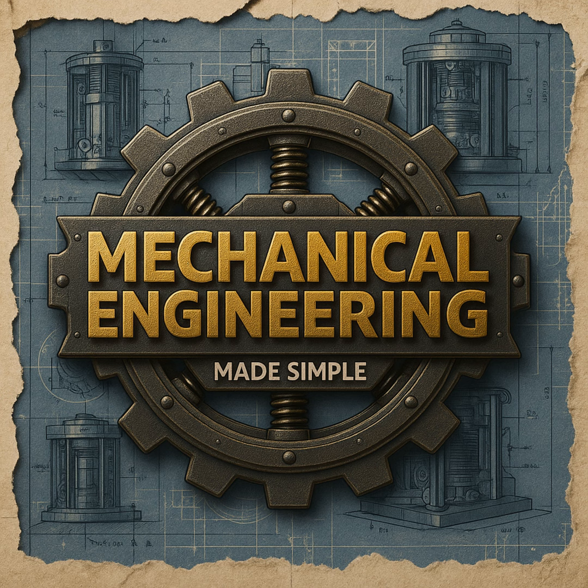Okay, low hysteresis. Second, you absolutely cannot have any dislocation motion within the material's crystal structure. So the stress you apply, sigma, has to be way, way below the material's yield stress, sigma yield. Much less than yield. Makes sense. And finally, how you assemble it is critical. There can be zero microslip or friction in any mounting points or joints.